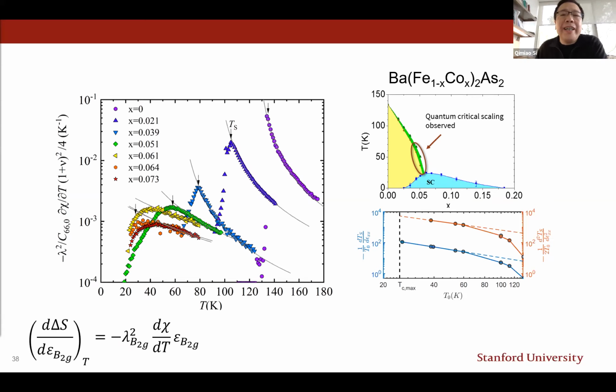Yeah, Matthias, beautiful talk. I was wondering whether I can connect this quantity, the elastocaloric effect, with something that has been thought about in the general context of quantum criticality, which is a Grüneisen ratio. If the system were responding to hydrostatic pressure, the Grüneisen ratio would be... this elastocaloric effect, as far as I can see, is precisely the strain tuning, stress tuning analog of the Grüneisen ratio in the case of hydrostatic pressure tuning?